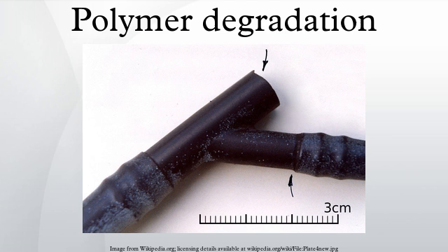For example, a forearm crutch suddenly snapped and the user was severely injured in the resulting fall. The crutch had fractured across a polypropylene insert within the aluminium tube of the device, and infrared spectroscopy of the material showed that it had oxidized, possibly as a result of poor molding.